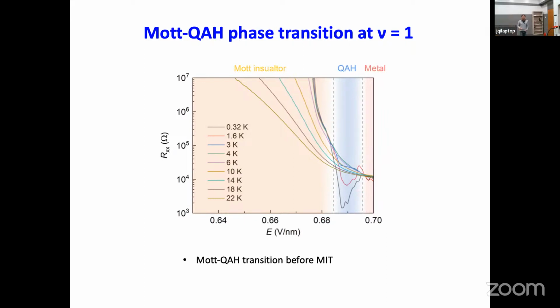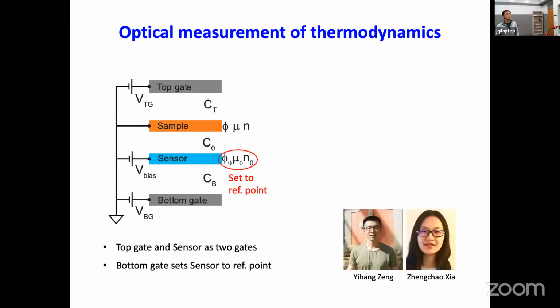Okay, so next, what I'm going to tell you is that we try to measure a little bit more carefully the thermodynamics around this Mott charge transfer insulator to Chern insulator transition. Let's see what we can learn from this thermodynamic measurement. To do that, let me tell you about a new technique that we recently developed, which uses an optical method to directly read out the chemical potential of a sample.